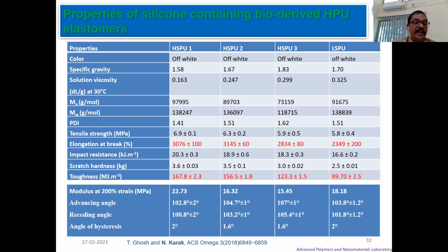If you see the advancing angle and receding angle, these are increased, and particularly the angle of hysteresis, which is the difference between the advancing angle and receding angle — if it falls below 2 degrees or near 2 degrees, then the surface becomes self-cleaning and hydrophobic. So the result is self-cleaning, and also flexibility.